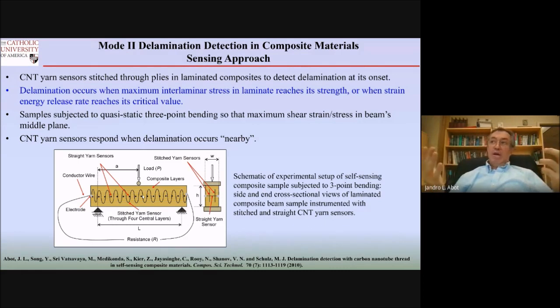Laminated composite materials are typically composed of carbon fiber and glass fiber, right? Carbon filaments, just for you, if you are not familiar, are 7 microns, and you form bundles, typically 3,000 or 6,000 filaments together in one bundle. So if you put in a carbon nanotube fiber, 30 microns, it won't do anything. The composite won't even see it there. And it's also friendly in the sense that a carbon material fits nicely with another carbon material. You probably have to isolate it because they're conductive. But the point is, this is a very friendly material to integrate. And you already have an embedded sensor in the structure.